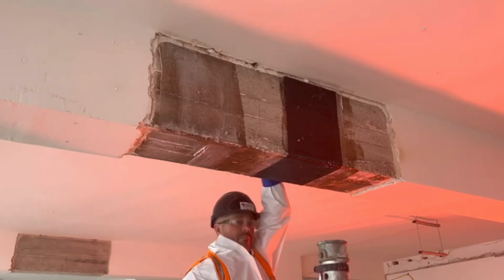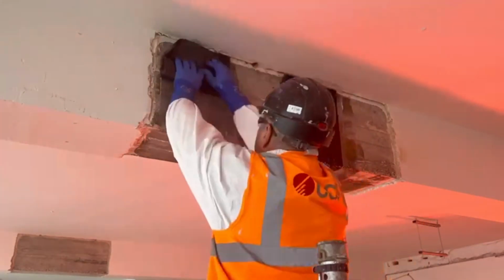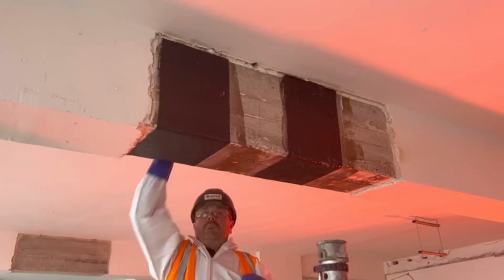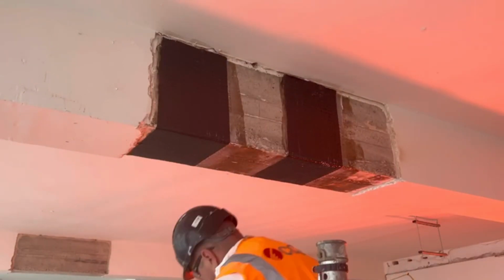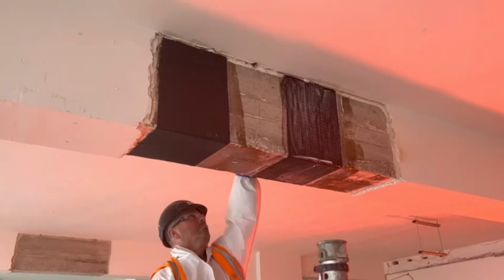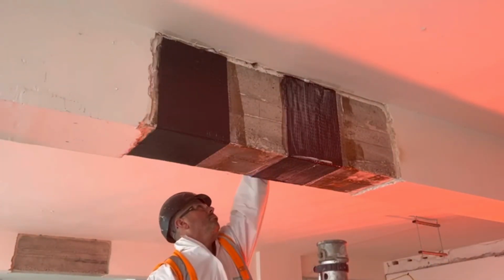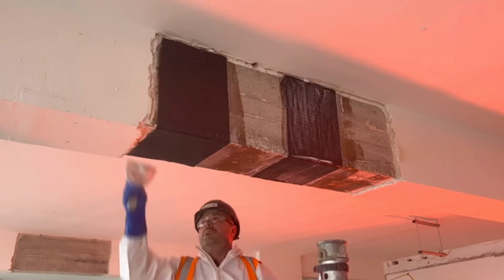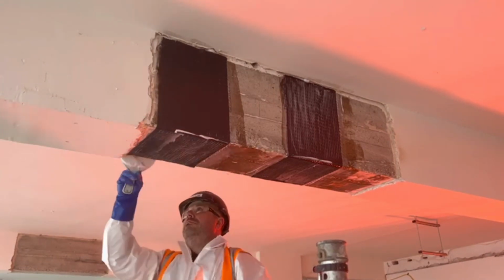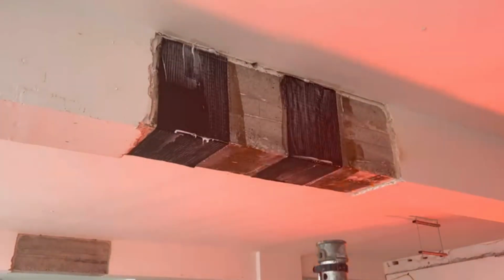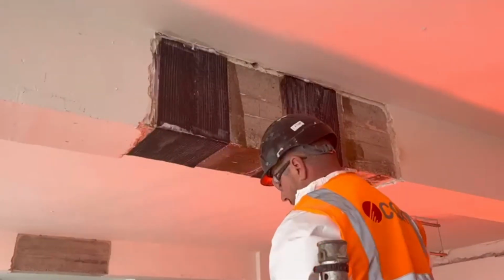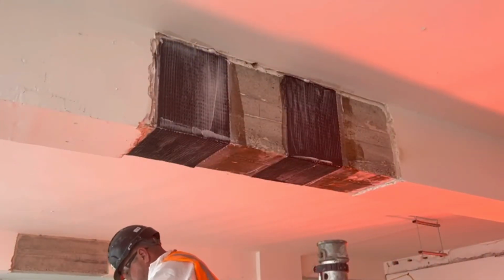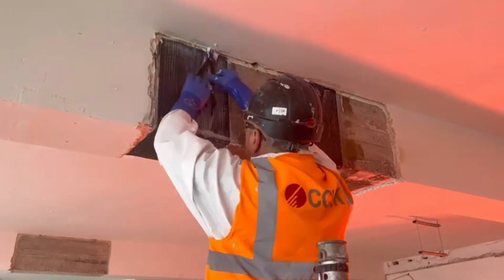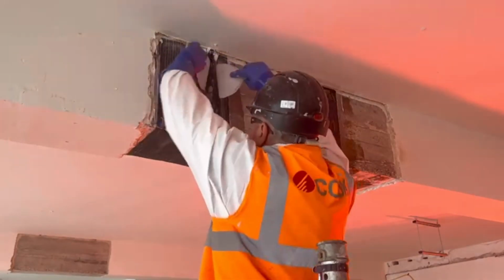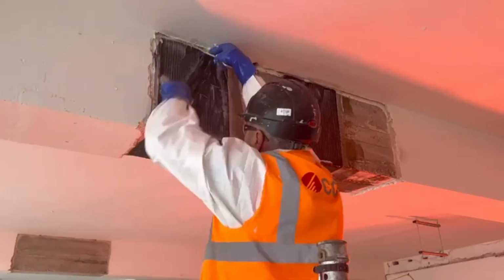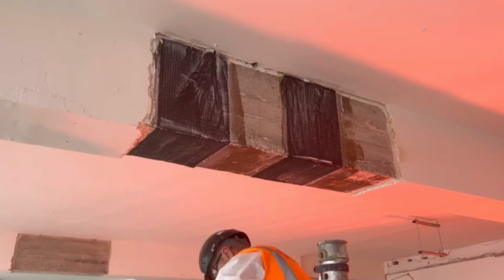So when they have applied the first layer, they will apply the second coat of epoxy, followed by, if there is any anchor installation, they will put the anchors in, otherwise they put the next layer of carbon fibre. But in this instance, because it's a shear strengthening, we use the carbon fibre anchors so that we have a full detailing there, like a closed loop. So that's why the anchors were installed. They'll put the anchor into the drilled hole, which is filled with epoxy. Then they splay the anchor onto the already laid layer, and then put another layer.